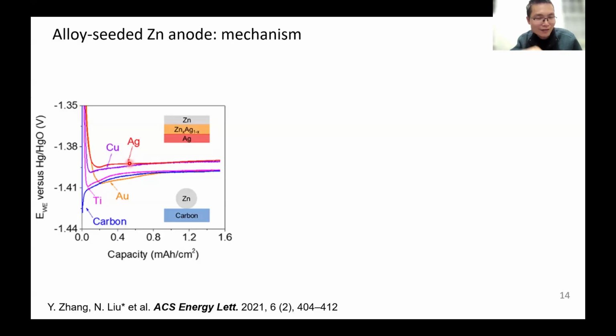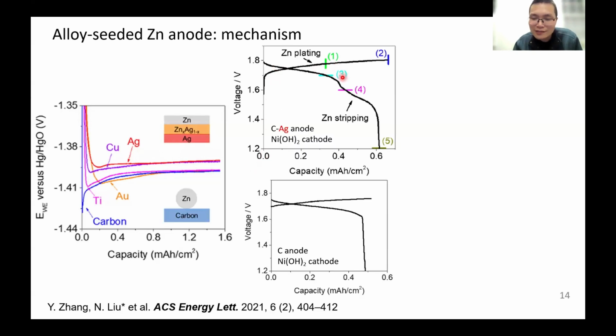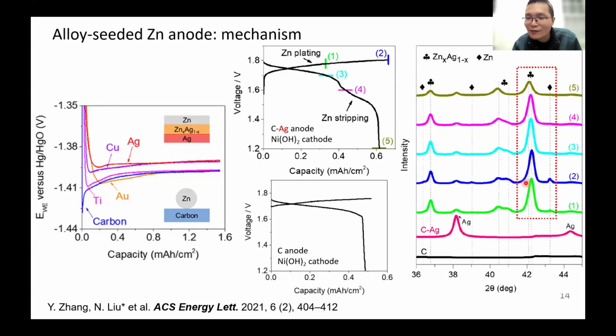That's how silver can spatially control where the zinc deposits. It forms an anchor and always brings zinc back to its nearby place. And you can control spatially where the zinc deposits. We did X-ray diffraction at different states of charge to confirm that you can detect this zinc-silver alloy after the zinc deposition. After the silver is saturated with zinc, metallic zinc will further form on top of that. So this confirms the mechanism.